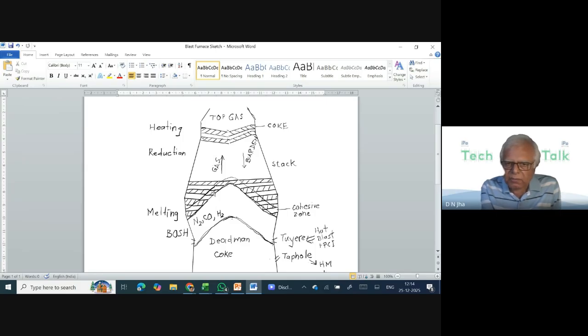So the top line of that is the softening line, and the bottom line here is known as the melting line. When we say melting line, then all the metallics have molten along this line, because below that you won't find the metallics, meaning ore plus pellet or whatever metallics that we have charged, in the solid form, because all that gets molten at this level. And this melting temperature depends upon the kind of ore that we have used.